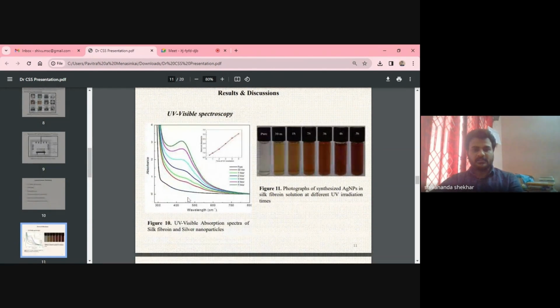Now the results and discussion part. First, UV visible spectroscopy. Here we irradiated the samples for different hours: half an hour, 1 hour, 2 hours, 3 hours, 4 hours, up to 5 hours. As the time of exposure increases, more nanoparticles are synthesized in the silk fibroin solution. When we put it under UV visible spectroscopy, we get a very nice SPR band around 400 to 460 nanometers. This is due to the formation of spherical nanoparticles, which we also confirmed in transmission electron microscopy. We also observe that the SPR band is slightly shifted from higher wavelength to lower wavelength. This is due to the formation of small-sized nanoparticles also.